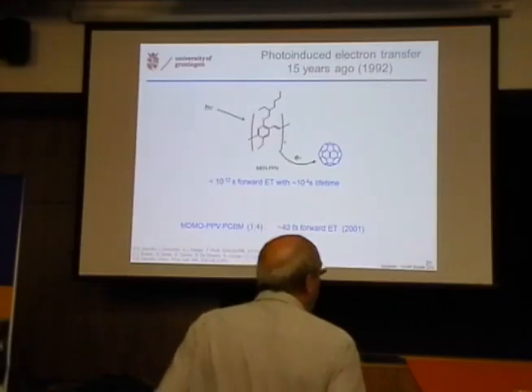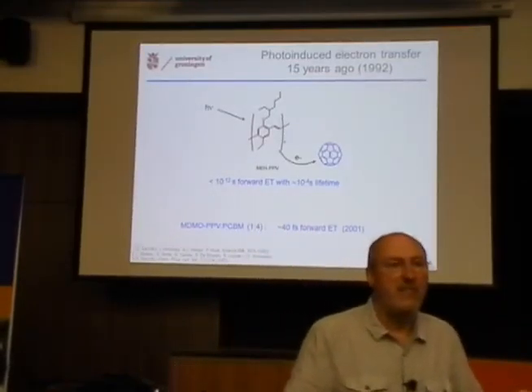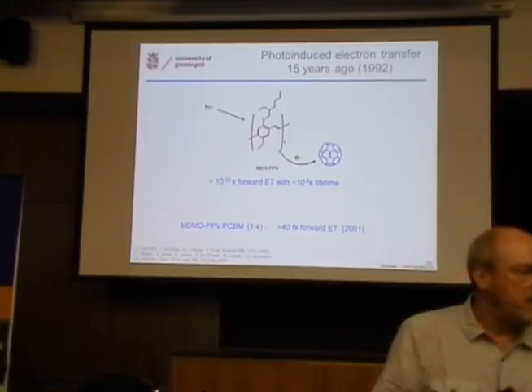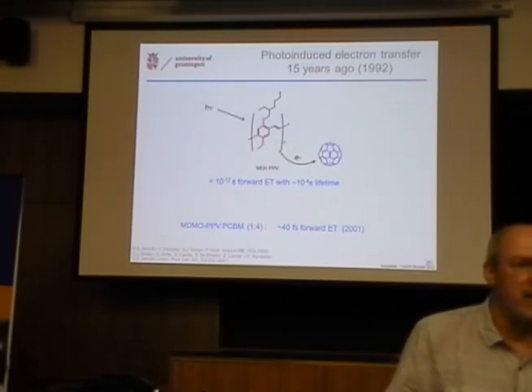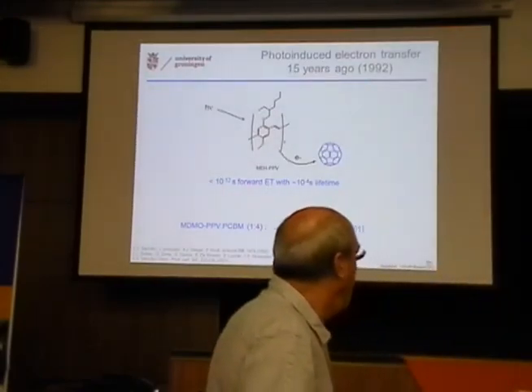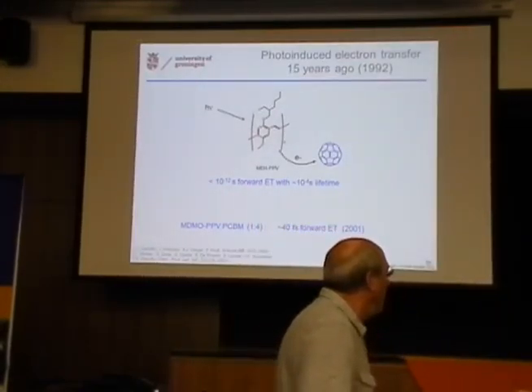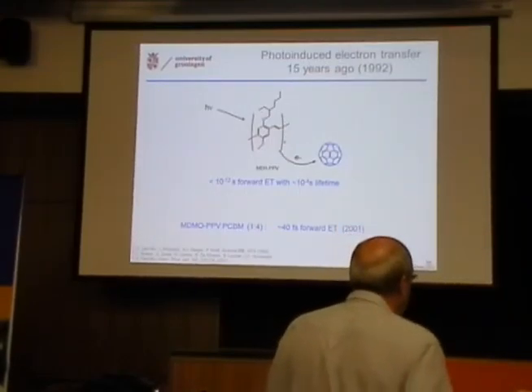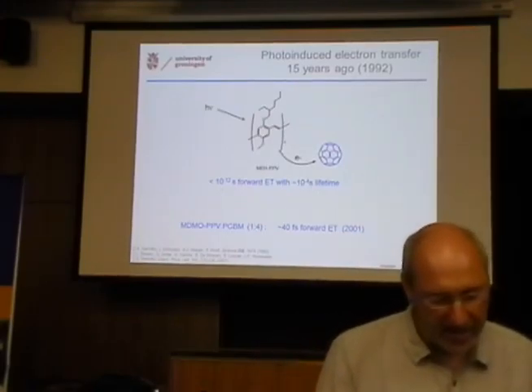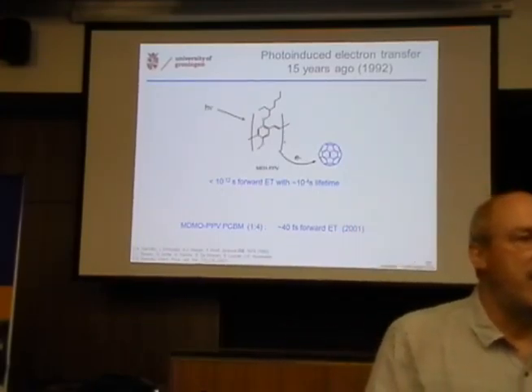And at that time it was clear you quenched the luminescence by a factor of 1,000. So you know it's an ultrafast process, because it must be something on the order of 1,000 times faster than the singlet lifetime, so it's around 1 picosecond, which is pretty fast. Everybody was happy with the picosecond until a little bit later, in 2001, with ultrafast laser spectroscopy. A lot of experiments were done in cooperation with an Italian group, and it was found that the forward electron transfer rate, in this case, is 40 femtoseconds, which is faster than the natural photosynthesis process.